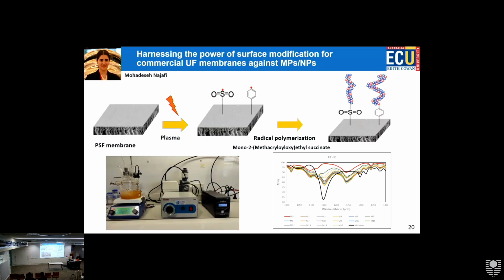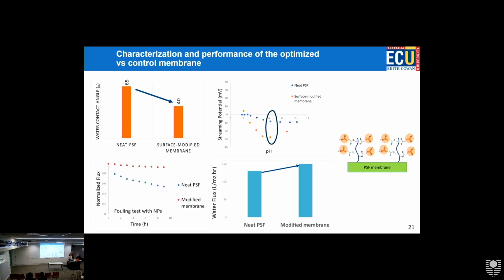With this polymer that she chose, it is highly hydrophilic and it has negative surface charges, which are both advantages in terms of repelling micro and nanoplastics. As I mentioned, they are negatively charged, so we want the same charge to repel them, and we want hydrophilic. We always want hydrophilic in terms of membranes. And she did several different material testing. In this one, we haven't presented all of the data, but this is basically the reactor where she adds this activated membrane under nitrogen and adds these monomers and then grafts, basically. If you have any questions, ask after that.